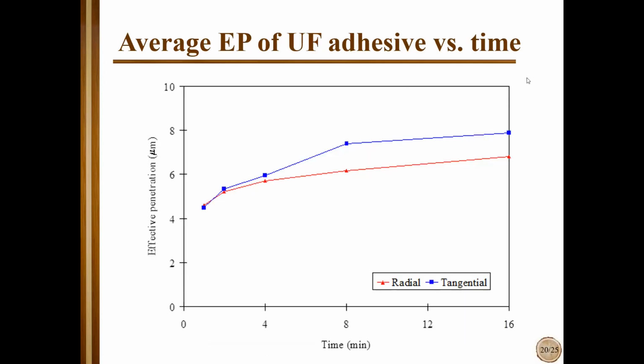Here are the results on adhesive penetration versus time, or assembly time. You see that most of penetration occurs in the first minutes. In the first 3-4 minutes, like 75% of penetration occurs. And then it's normal that it doesn't go further because typically after several minutes, adhesive becomes dry and less mobile, so it cannot penetrate anymore. Also, what is important here, effective penetration is quite low, let's say 4 to 8 micrometers. Before we saw like 40 or 60 micrometers. The main difference here is that we don't use any pressure. It was only applied by a roller on the surface of wood, and then we estimated adhesive penetration without any pressing.